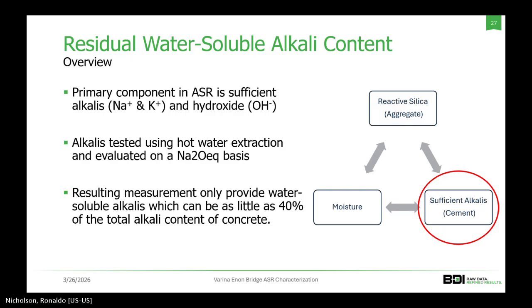We also performed residual water-soluble alkali content. Again, it's another one of the ingredients for ASR. So understanding how much alkalis were left in the system helped the advanced models for remaining ASR expansion, where the primary component, again, is the alkalis in the cement paste, which are sodium and potassium hydroxide. The alkalis were tested using hot water extraction and evaluated on a Na2O equivalent basis, where the resulting measurement only provided water-soluble alkalis, which can be as little as 40% of the total alkali content of concrete. Again, it's one of the limitations of the test.